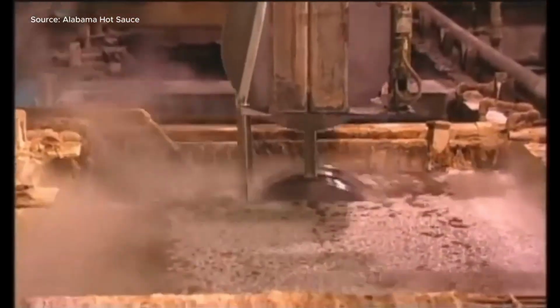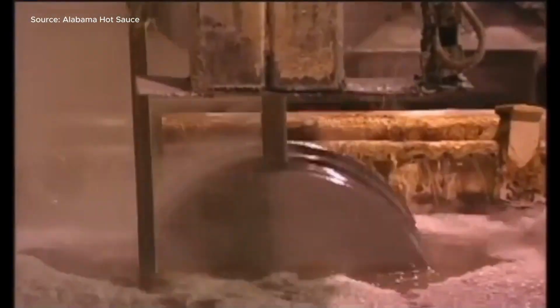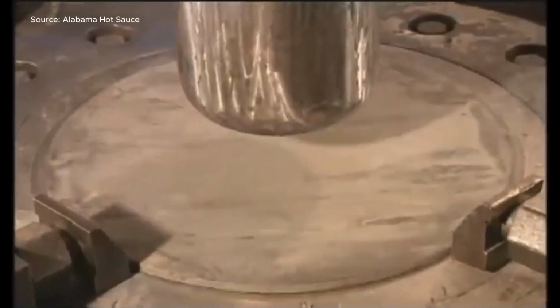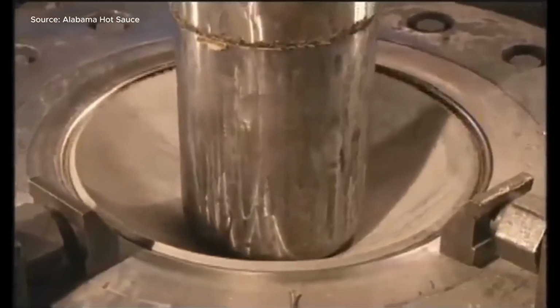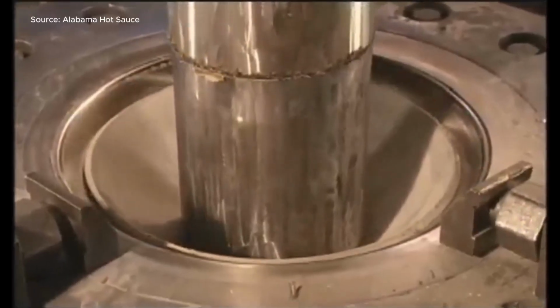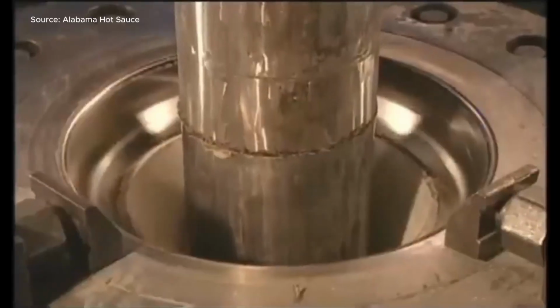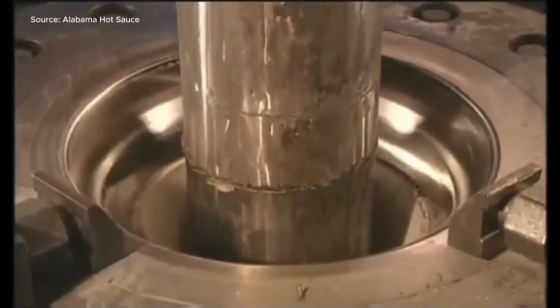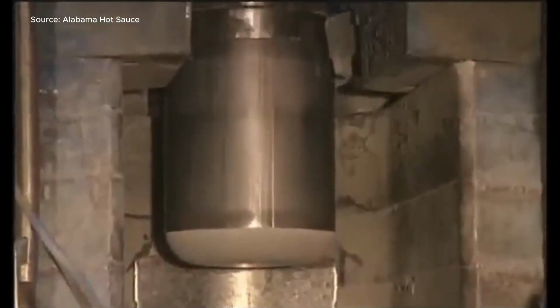The production of Worthington X-Series steel scuba cylinders begins with the preparation of high-grade chromoly alloy, which meets strict requirements for grain structure, impurity levels, and micro-cleanliness. The raw material undergoes deep drawing and ironing operations, using up to 800 tons of force in the first press and 250 tons in the second.